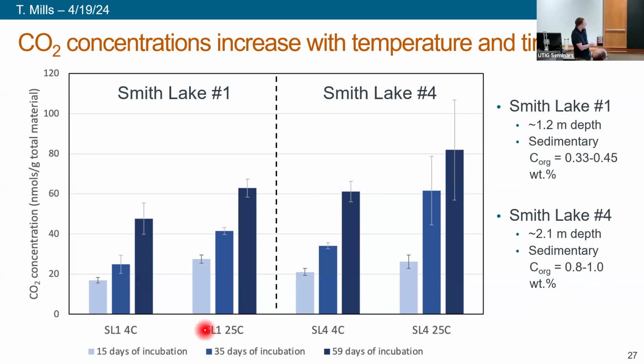And so our plot here is showing CO2 concentration in nanomoles per gram of total material. This total material is the water and the sediment. We'll be readjusting these values to account for just the dry sediment, but the samples are still incubating, so we can't burn off all the water yet. On the left side, we have our Smith Lake samples. These clusters show our incubations at 15 days, 35 days, and 59 days for Smith Lake 1 at 4 degrees C, Smith Lake 1 at 25, and then Smith Lake 4, et cetera.